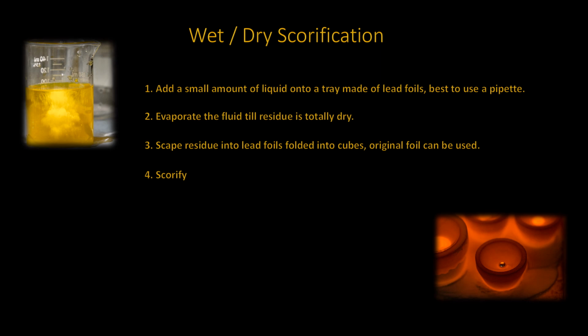If you want to save the silver, the gold should be precipitated first, filtered, washed, and dried, then mixed with the granulated lead and borax to be scorified. The remaining solution to be evaporated for the silver, then mixed and scorified.